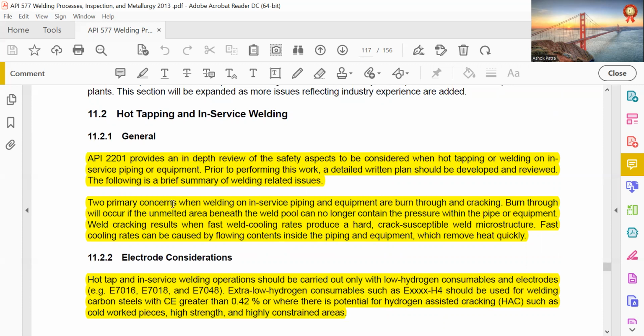Two primary concerns when welding on in-service piping and equipment are burn through and cracking. Burn through will occur if the unmelted area beneath the weld pool can no longer contain the pressure within the pipe or equipment. Weld cracking results when fast weld cooling rates produce a hard, crack susceptible weld microstructure. Fast cooling rates can be caused by flowing contents inside the piping and equipment, which remove heat quickly.